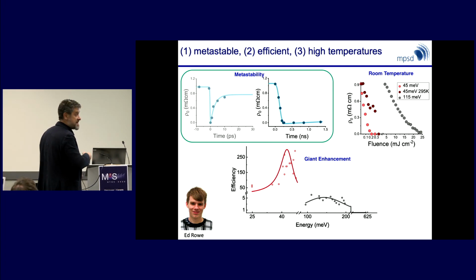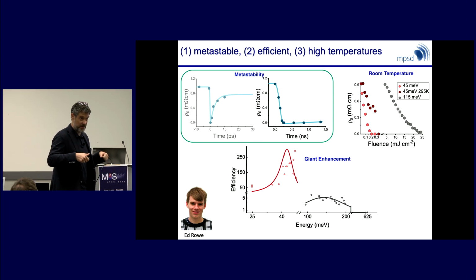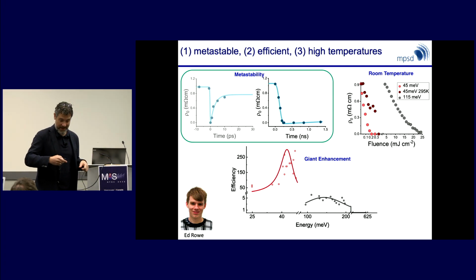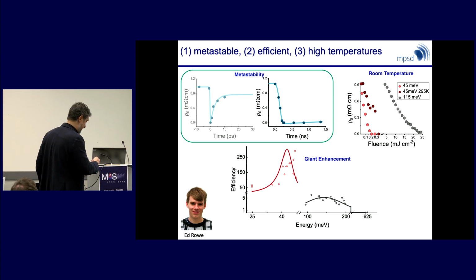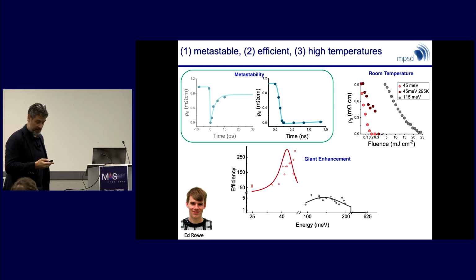So in the last 2 years, what we found is that by pumping in the right way and harder, we can find a metastable state that lives for about 10 nanoseconds, and also with an electrical resistance that is compatible with 0. The efficiency has gone up by 100-fold, and the effect appears to survive up to higher temperature scales than the 100 and 150 Kelvin that we discussed before.